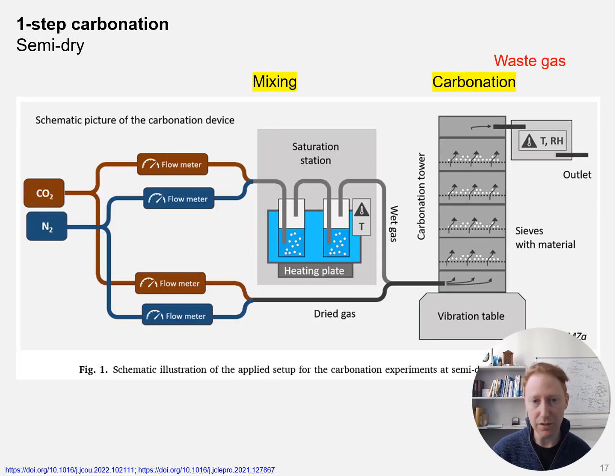In the humid or semi-dry process, rather than immersing the carbonatable material in solution, we expose it to a humid CO₂-rich gas, for example in a carbonation chamber. The material carbonates quite quickly in the presence of this humidity, and because there is less water, it requires less drying after carbonation than in the wet process. There is also some wet CO₂-depleted gas that needs to be circulated or managed in this system too.